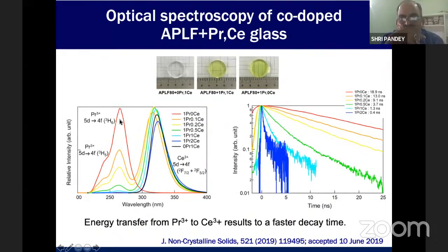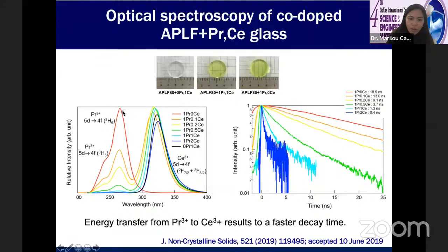And indeed, if we look at the luminescence intensity, if we increase the ratio of cerium from 0 cerium to 1% cerium, the intensity of the praseodymium emission decreases. And that's because energy is transferred to the cerium ions. We also see, as a result of the energy transfer from praseodymium to cerium, that the decay time of praseodymium becomes faster. So the red line is pure praseodymium. The blue decay is with 2% cerium. So we are able to achieve a very, very fast decay time of 0.4 nanoseconds.